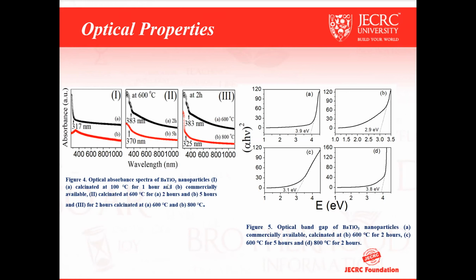And with the help of that, we have taken the extrapolation, and we found the band gap of the synthesized barium titanate nanoparticles. So it seems that as the calcination temperature increases, the band gap increases, and barium titanate nanoparticles synthesized at 800 degrees centigrade for 2 hours have a band gap nearly approximate to the standard one, that is 3.9 electron volts.